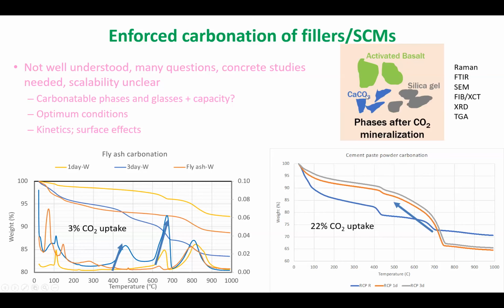So what does the phase assemblage or the morphology look like after the process? And by the way, it doesn't look anything like that, that's for sure. But essentially, you're forming calcium carbonate, right? Is this just a very thin layer of calcium carbonate, or is it a pretty thick layer? Is this a very dense layer, which is causing it basically to stop at some point, right? Does this start off at some kind of a defect? Or is it only the most prone phases to carbonation that are reacting? So a lot of these questions are not answered.